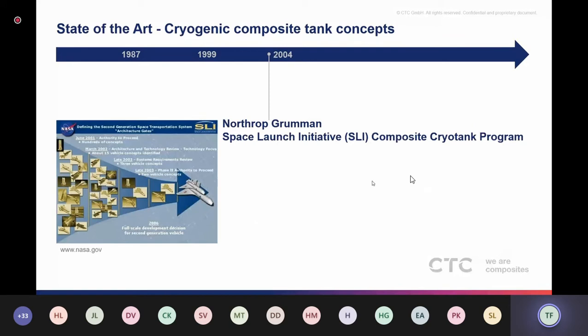Based on these results, in 2004, Northrop Grumman built another prototype of a CFRP hydrogen tank for the Space Launch Initiative program. Here 3 innovations were used. One was that thinner carbon plies were used, which helps reduce the number of microcracks. I will come to this thinner ply topic a little bit later on again.